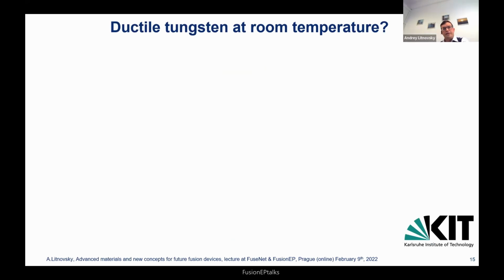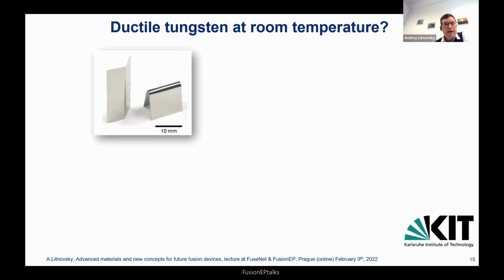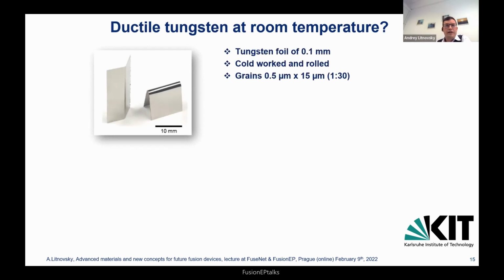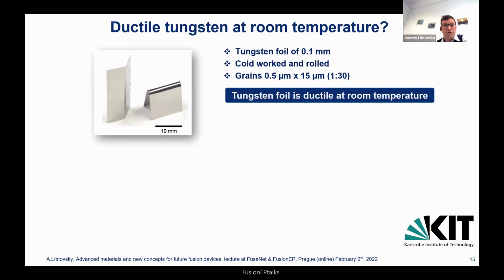Speaking about pseudo-ductility, what about a different technology? This was actually brought by our colleagues at Karlsruhe, who noticed at first glance a very simple example. If you have a tungsten foil which is thin enough, and you know tungsten as such is a tremendously brittle material, you can really put this on the floor and it will crack or break apart. But if you take this foil, which is cold worked and rolled, and you see the grains are highly inhomogeneous, you can actually bend this roll, nothing will happen. So it is ductile even at room temperature.